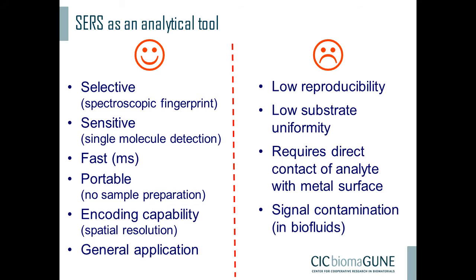Another point is that the analyte has to be very close to the metallic surface. And so sometimes we were saying the analysis is restricted to molecules that have some chemical affinity for a metallic surface. Nowadays, we have tricks to help solve that problem, but it's still a problem that has to be solved. Another point is, especially if you're going to bioapplications, in biofluids there are plenty of other molecules around. So if you're interested to study, for example, a cancer biomarker, you need to find really the peaks which are specific to that marker. And if you have other proteins or lipids floating around and they get in contact with your metallic surface, they will, on one hand, bring many more vibrational peaks to the spectrum, so you will have a hard time identifying the one you're trying to identify. On the other hand, they may actually block the surface, so your analyte may not be able to reach contact with the metal.